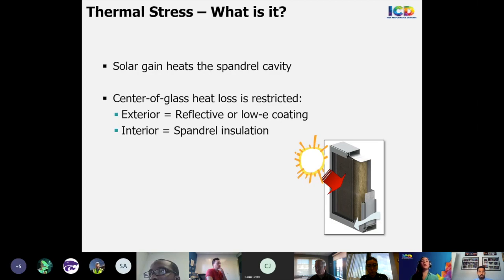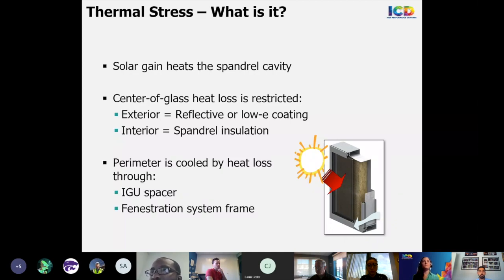The solar gain, coupled with the restricted heat loss, allows the center of glass portion of the spandrel glazing to become very warm. And at the same time, the surrounding framework chills the perimeter of the glazing, so the warmer center of glass area expands relative to the colder perimeter, creating tensile stress. And it's when the stress exceeds the strength of the glass that breakage can occur.